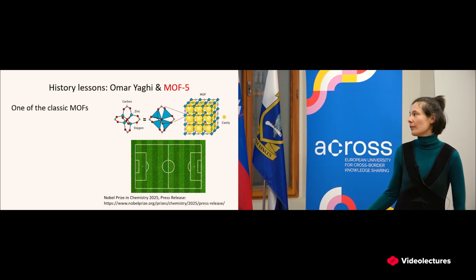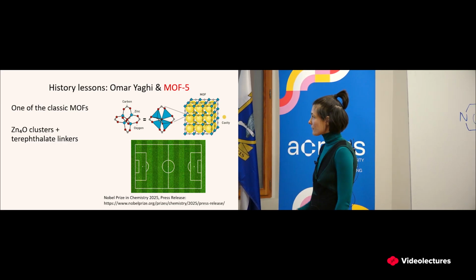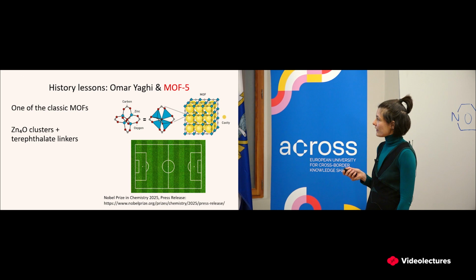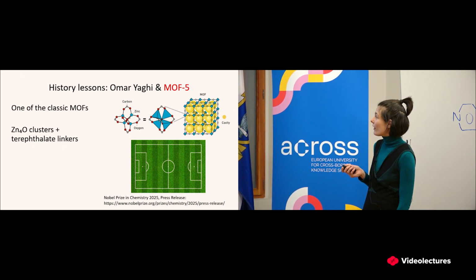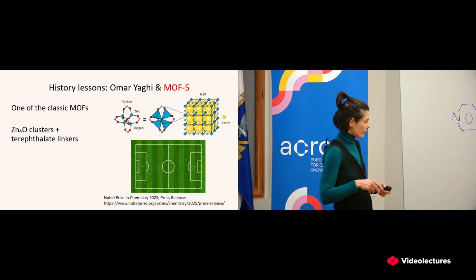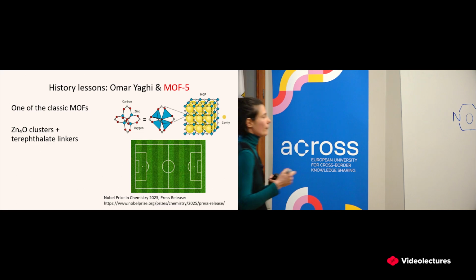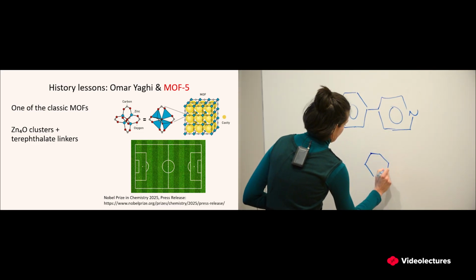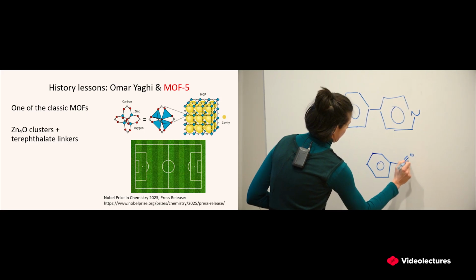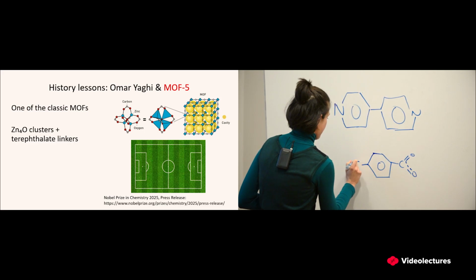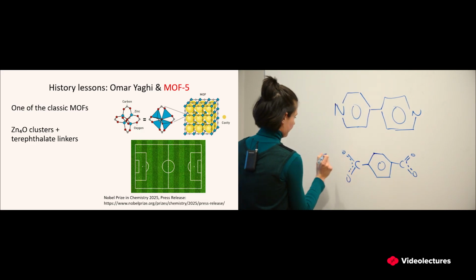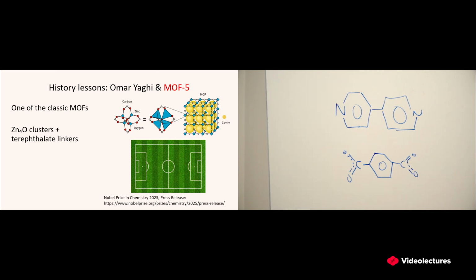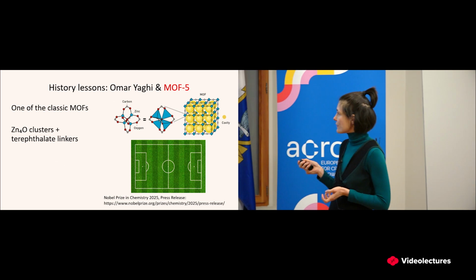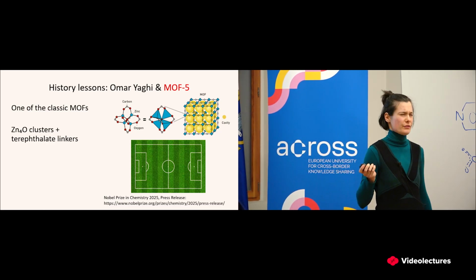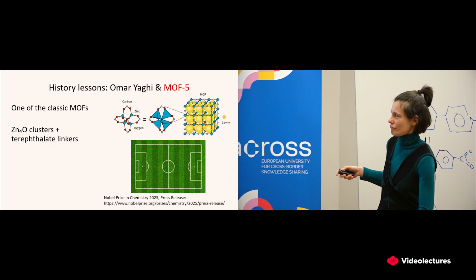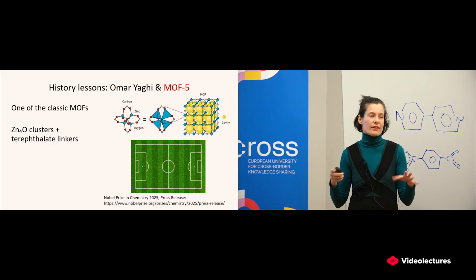So this is a classic example of a metal organic framework. It contains zinc ions, and as you can see in this cluster, each of the zinc ions is linked to 4 oxygen atoms that are part of the linker. So the terephthalate linkers, this is just a benzene with 2 carboxylates. So it looks like this. Two carboxylates. And the white spaces that you see here, the yellow spheres you see, this does not really represent any particular gas or metal or anything. This is just to show the cavity. It's to emphasize the cavity size.